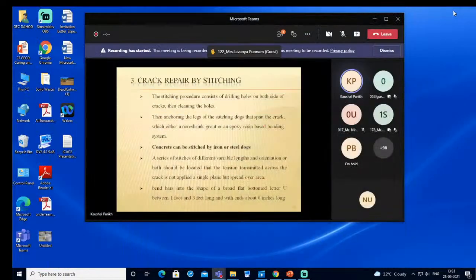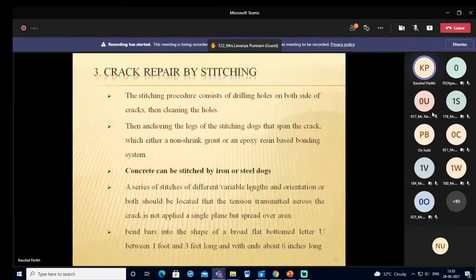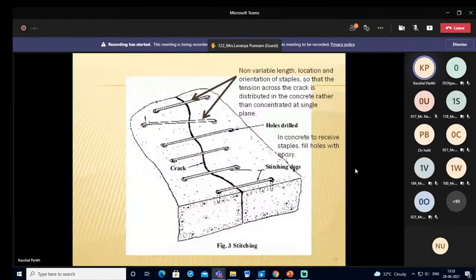Flat bottom, a little U between the 1 foot and the 3 foot long, and which ends about 6 inches long. So the figure clearly indicates here that the crack is there, and the variable length as well as the location and the orientation of the staple, so that the tension across the crack is distributed in the concrete rather than concentrated in a single plane. So it is not necessary that there be half of the portion on the one side of the crack and half on the other side.